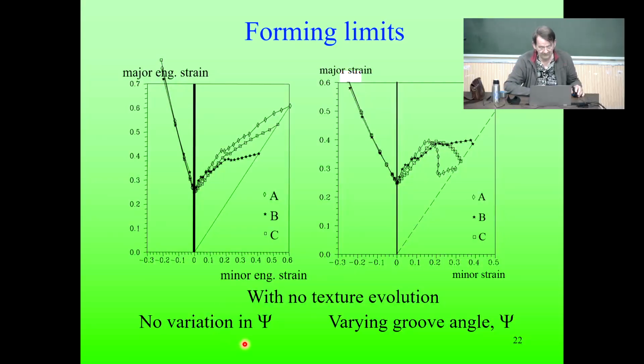So here we have the results. The predicted results here are shown when texture evolution is not considered and no variation in the groove angle. It's like the old calculation in which you don't consider texture evolution. At least the texture itself was considered. So there is effect: texture A, B, and C lead to very different FLDs. You see, very different. So, for example, the B texture, which is not a cubic, has the lowest formability, and the A and C, which contain the larger cube component, had much better formabilities in sheet metal forming. So the texture dependence is very high on the positive part of the FLD, but very small in the negative part, you see, the prediction.